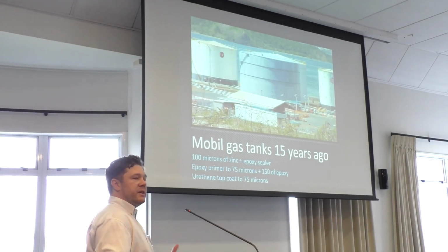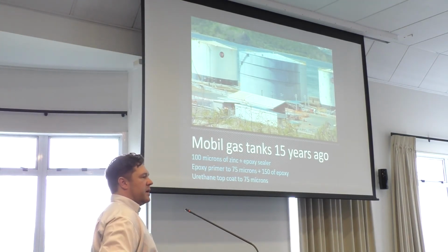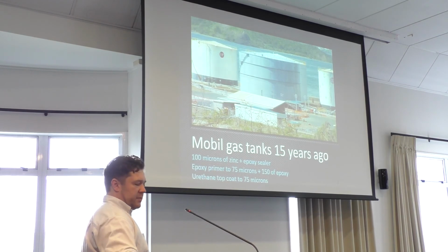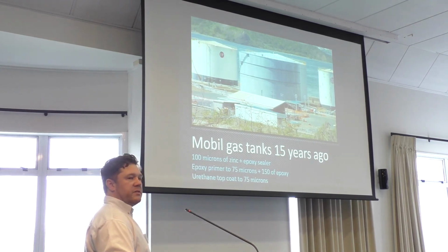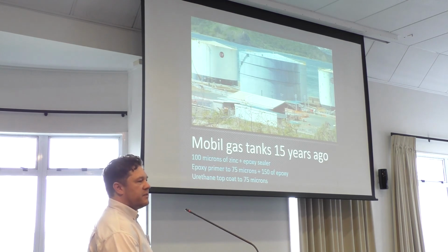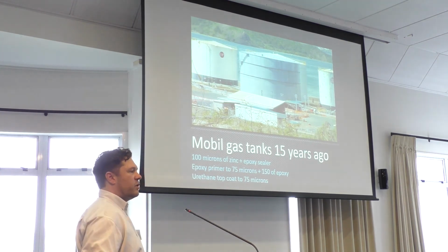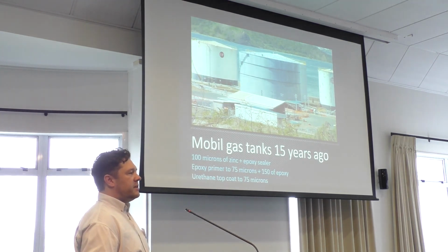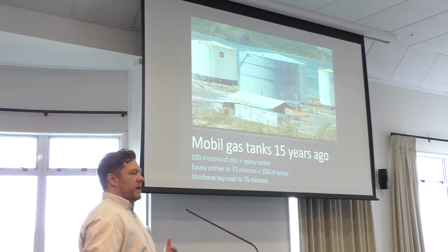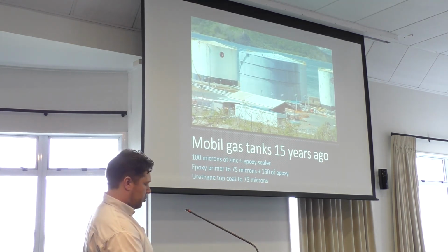Sometimes more metal spray isn't better for you. If you want to put the paint on top, if you put 100 microns of metal spray, in most situations that's going to get you a really good life expectancy out of it. Going to 150 or 200 microns is just going to give us a bit more of an opportunity to have air trapped in that coating and run into issues with it. More isn't always better.